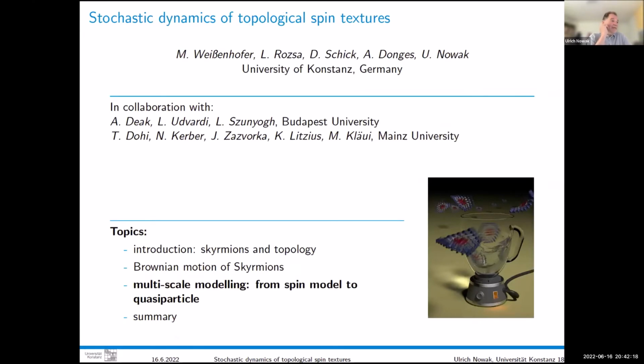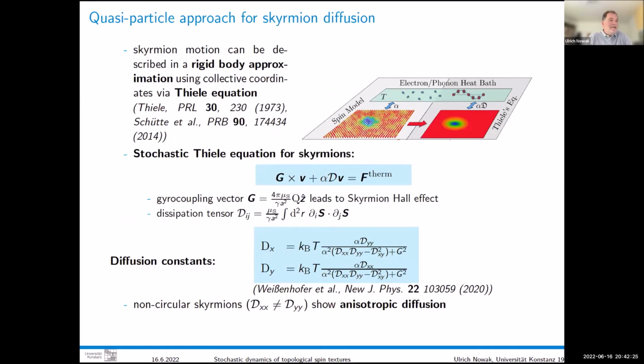Okay, so how can we understand that a bit more in a multi-scale modeling picture? You can treat the whole skyrmion in this magnetic heat bath also as a particle that follows an equation of motion. So we don't have all the equations of motion for each spin, but just one, assuming that the magnetic texture of the skyrmion is rigid. And that is called the Thiele equation. The Thiele equation exists also for domain walls and vortices and whatnot. You can do that with all sorts of stable textures. You assume there is a certain ground state texture, let's say, and that does not move anymore. And then you average out all degrees of freedom, and then you come up with an equation of motion for the center of mass, maybe also for other quantities. In the case of a domain wall, the angle could get another equation of motion also.